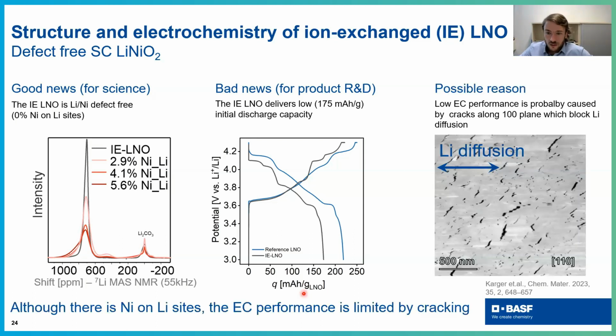If you look at the cross-sectional TEM, in an orientation which is chosen in a way that you see the lithium diffusion planes, you see everywhere a lot of cracks, meaning that if lithium is trying to diffuse in or out, it stops at some point because there will be a crack on the way. And this severely limits the diffusion. And why is that? Well, I have to say that these cracks are not visible in the sodium nickel oxide, which we used as a precursor. So they really appear after ion exchange.